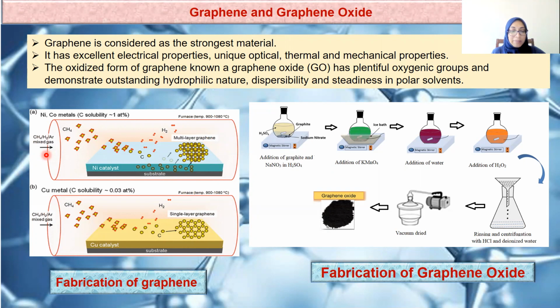Here, graphene can be fabricated by thermal CVD on polycrystalline nickel film. As shown here, around 500 nanometer thick nickel film was evaporated on a substrate, that is a silicon substrate, and it was annealed at a temperature of 1,000 degrees centigrade for approximately 20 minutes with argon and hydrogen. Nickel grains of 5 to 20 micrometer in dimensions were formed. And after chemical vapor deposition for about 10 minutes at 1,000 degrees centigrade, using methane and hydrogen, graphene was formed on nickel, and the size of each graphene is limited by the grain size of nickel. And here we are using copper catalyst instead of nickel film.